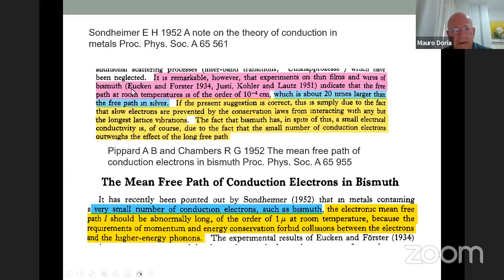Again, I like to emphasize this. These are papers from 1952 by Sondheimer and Pippard, who discovered the Pippard relation that determines the coherence length. Look at Sondheimer. It says it's remarkable, however, that experiments on thin films and wires of bismuth indicate that the free path at room temperature is of order of 10 to the minus 4 centimeters, which is about 20 times larger than the free path in silver. In fact they speculate on why the mean free path is so large. Of course, there are not many collisions with phonons. They say that momentum and energy conservation forbid collisions between the electrons and the high energy phonons. This is a way to put things.